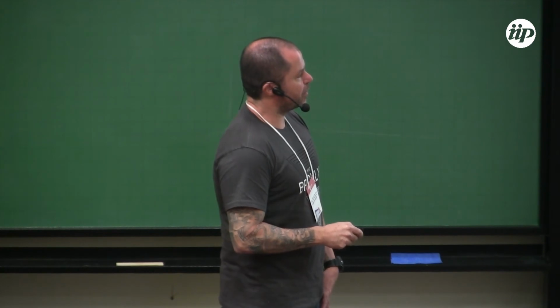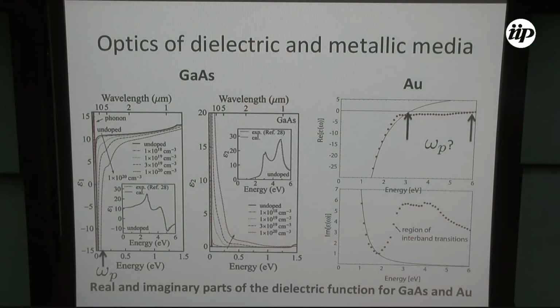So the problem with metals is, the solid line here is the expression that we obtain for the free electron gas, for the dielectric constant of a free electron gas. And you see that for gold, for example, it follows very nicely. But here we have the so-called interband transitions. And they get things complicated because they don't allow the dots to cross, and then you would go to the good region of transparency. But they keep the dots here way below until 6 electron volts, which is way higher than the visible. And then you cannot make it transparent.